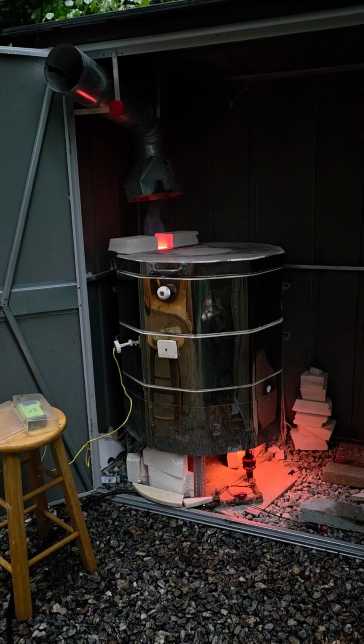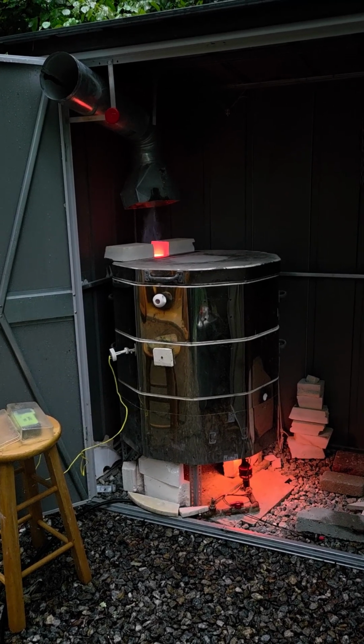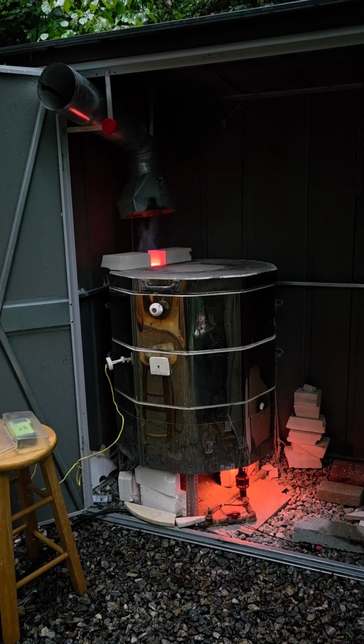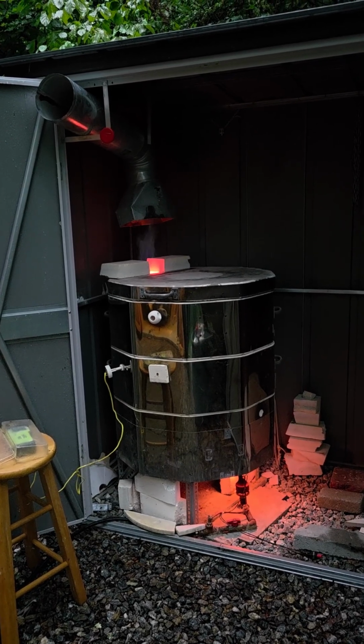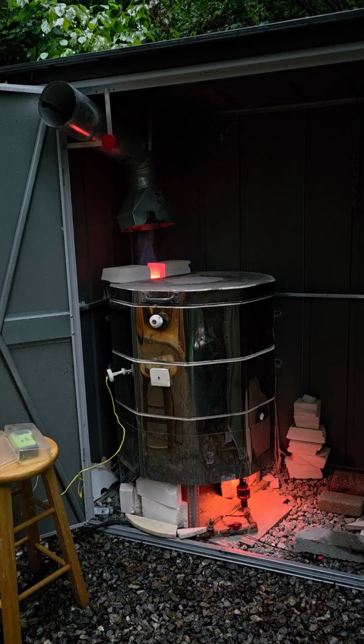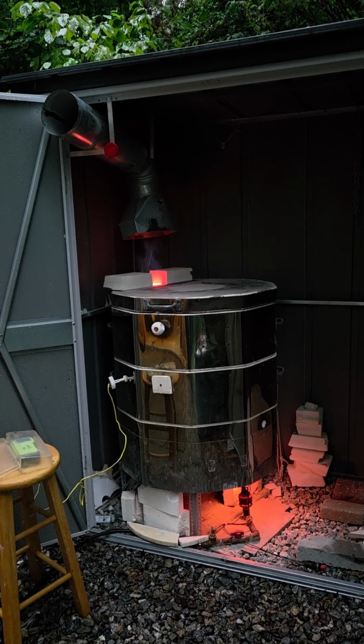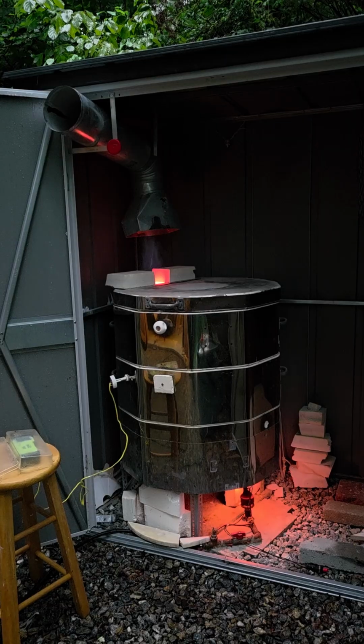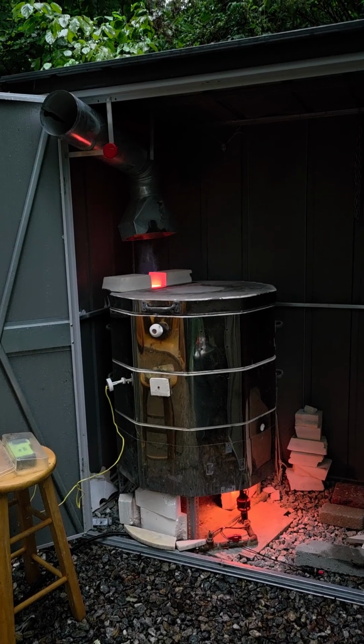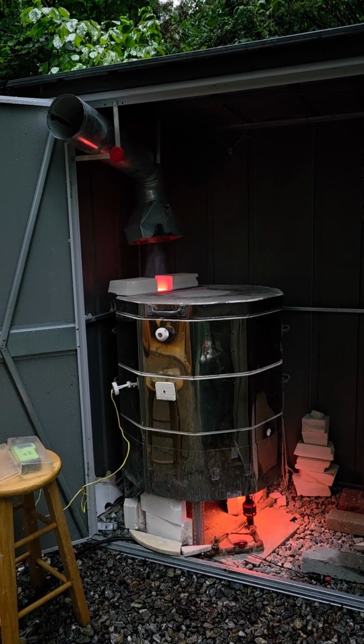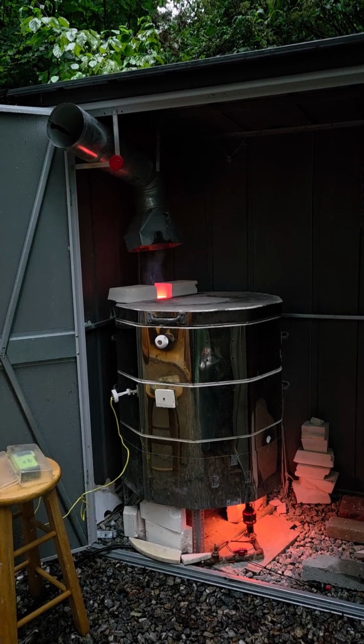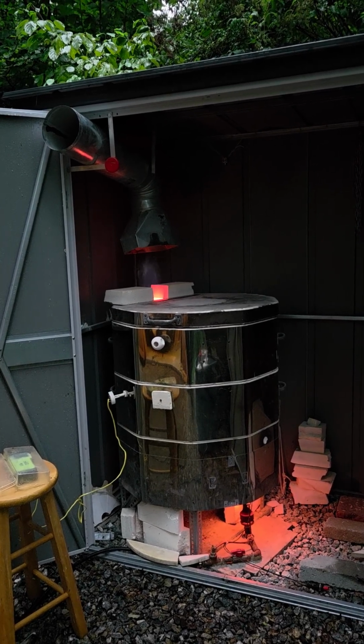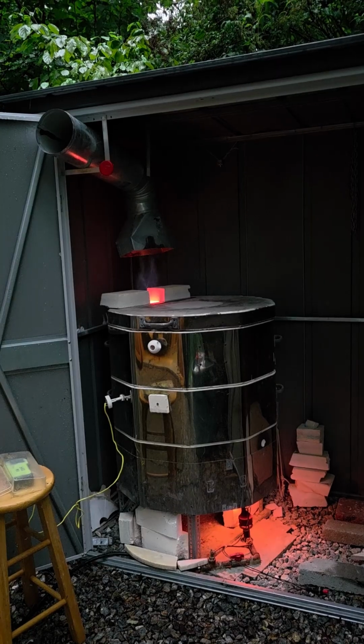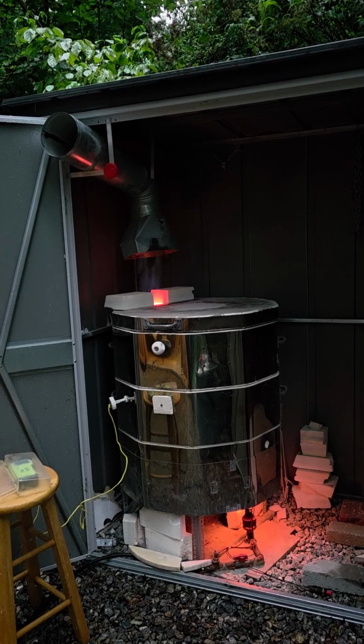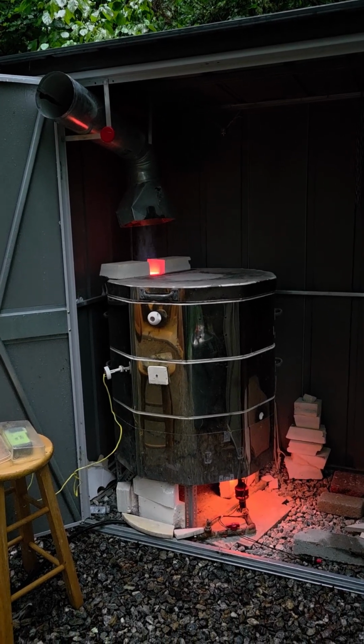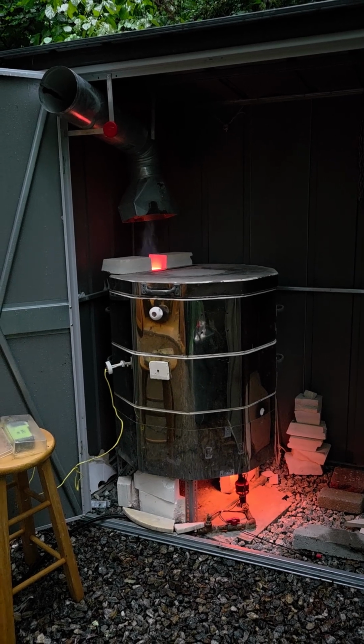Here's another image of the reduction flame, and what I did was I just darkened my video to kind of match what it was like outside, and this is more what one would see in reality for a reduction flame. So it's not super intense at this point. It's at about 1,040, 1,035 degrees centigrade. So that's kind of what one is looking for.